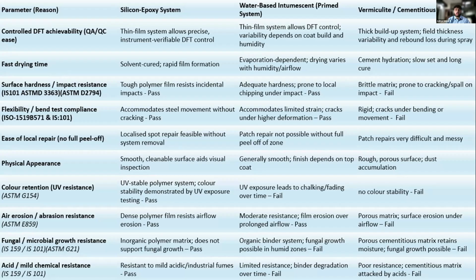Moving on to the physical appearance, about how the coating looks, as steel structures are used inside the buildings to show as an aesthetic as well. So the silicon epoxy and water base offer a generally smooth finish depending on the top coat of the customer's choice. And then vermiculite coatings offer a rough porous surface, and also dust accumulation can happen over time. Then color retention, that is judged by UV resistance at ASTM G154, where the silicon epoxy passes the test, but in water-based chalking or local peeling off can be seen, and vermiculite has no color stability. Air erosion as per ASTM E859, silicon epoxy passes the airflow erosion test as well as water-based. The vermiculite coating does not. It creates a dust form of coating and does not pass the air erosion test.